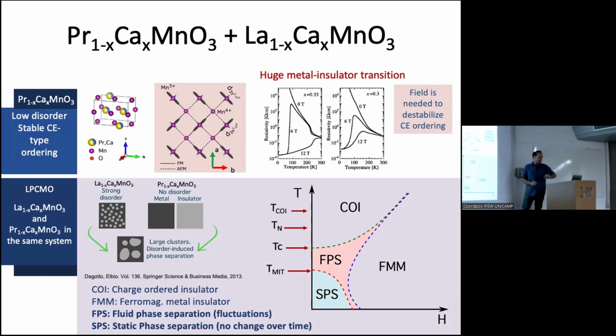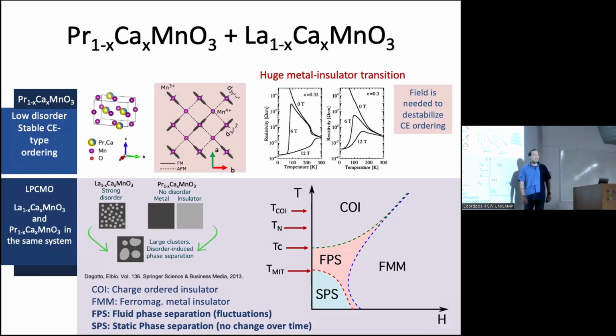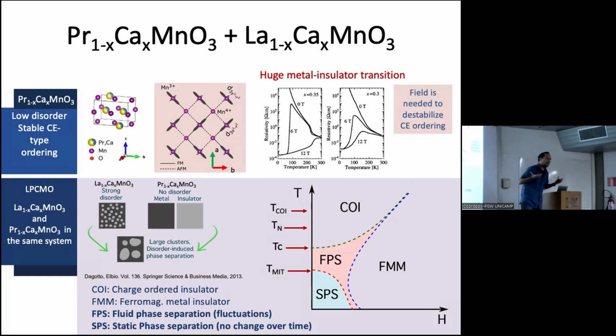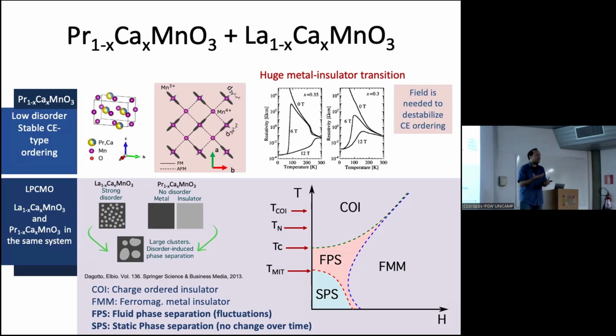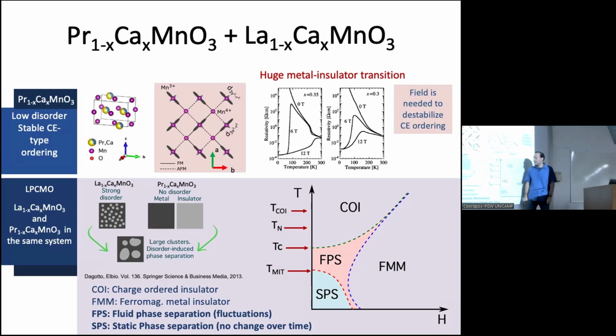Just to give you a summary. Oh, so there is a bunch of transition temperatures here. So this sample has the most phase transitions that I've ever seen in a material. So it has something that is a charge ordered insulator. It means that the charges ordered in the manganese 4+. Then it has an antiferromagnetic ordering. This is the Néel temperature. Then it has a Curie temperature because then from the antiferromagnetic matrix emerge these ferromagnetic domains, and those ferromagnetic domains they interact, they grow, and then they order, and there is a Curie temperature for that order, and then there is a metal insulator transition.